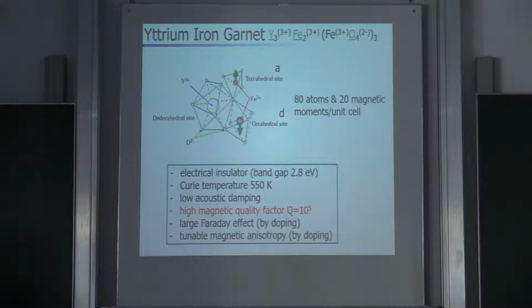Anisotropy can also be tuned. Usually pure YIG has a very, very small anisotropy. But by doping, you can get anything you like. You can also get it perpendicular, for example. So the magnetic bubble memories a long time ago were based on YIG with a perpendicular magnetization.